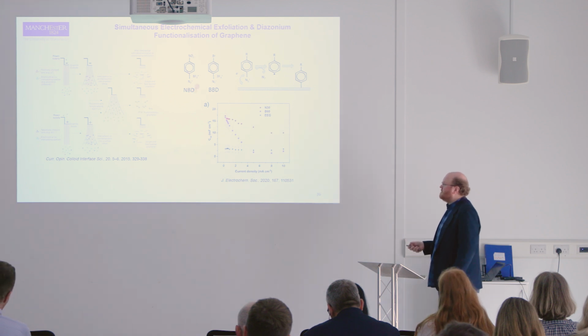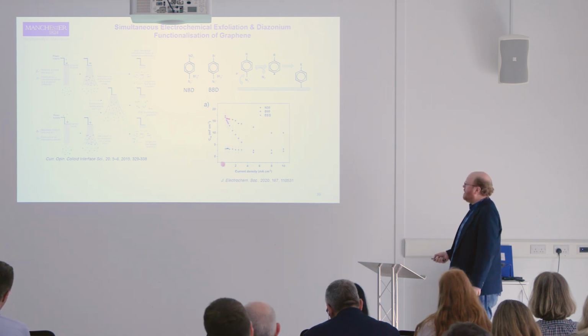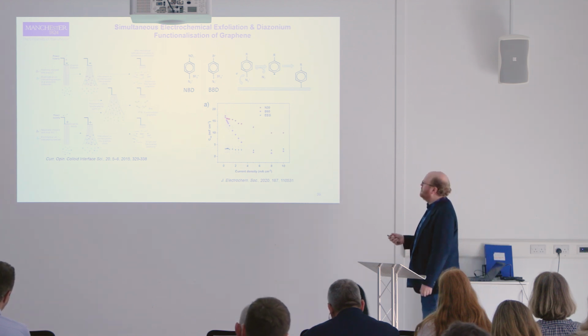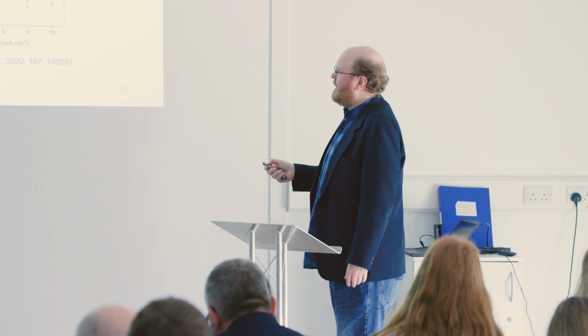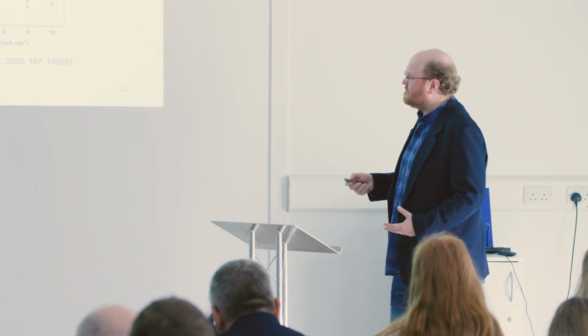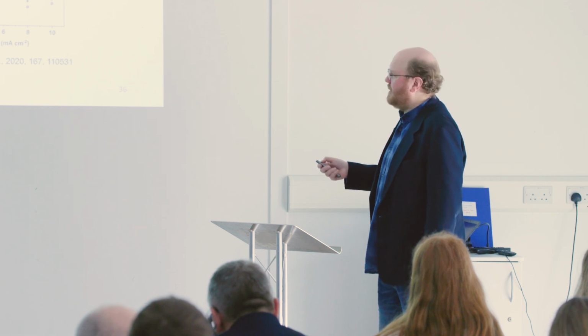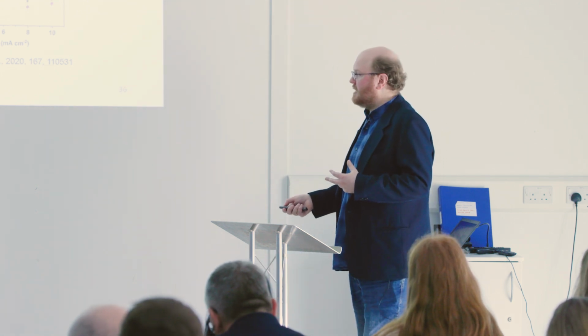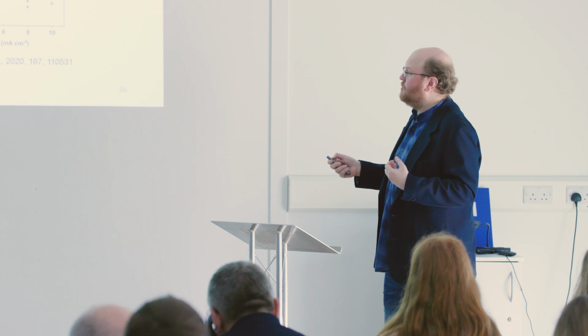And so if we make a device out of this exfoliated functionalized material, for graphene, its capacitance is very, very low. It's down here at about 3 or 4, basically not very good. If we functionalize these, we see this massive improvement, particularly at low scan rates. But what we do see is that it drops very quickly, at least in the case of the bromo. In the nitro, it's better. And that's really the trade-off with pseudocapacitance: yes, the energy you're getting out is much higher, but it's a slower process. So as soon as you increase the current density, which is the same as increasing the cycling rate, the rate of charging or discharging, the performance can drop quite quickly. So these are good for low power applications where you need high energy.